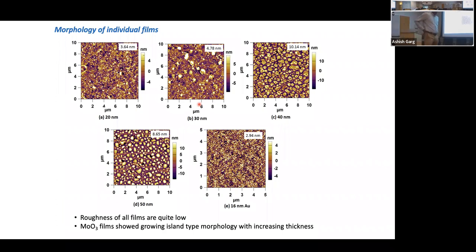So you evaporate MoO3, but the substrate is kept at room temperature. So it's not a high temperature process. Okay. So is there an impact on the crystallinity, or is it nearly all amorphous? Well, they are sort of semi-crystalline. They are not really very crystalline. If you heat treat them at high temperature, they tend to increase their roughness, which is not really good for the transmission characteristics. So it's a challenge. So it's all about thickness and making sure you control the... It is about thickness and the temperature of deposition. Yes. Okay. Thank you.